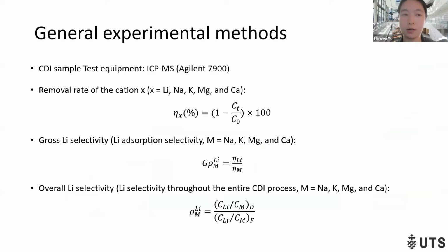The key parameters used to evaluate the CDI performance include the removal rate, which tells us how much of a specific ion is adsorbed during the adsorption step, and the gross lithium selectivity, also called lithium absorption selectivity. It reflects the relative absorption preference of lithium over another competing ion. In contrast, the overall lithium selectivity captures the entire CDI process, including absorption and desorption. That means GLS shows how selectively lithium is absorbed, while the overall lithium selectivity tells us how well lithium is retained and separated through the whole process.